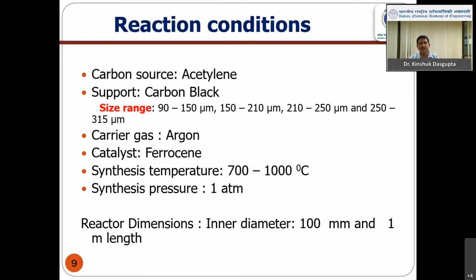So people generally they use like alumina, magnesia. These are costly materials and you require further processing steps to remove those materials from carbon nanotube. But in carbon black, first of all, carbon black is very cheap, and also you can remove them very easily, that I will discuss. So that is why we have used the carbon black. So by using these materials, you can really make the product a cheap product. If you use a raw material which are cheap, then you can end up with a product which are cheap. And carrier gas, we have used argon, catalyst, ferrocene. Ferrocene is a organometallic material which on heating will release iron nanoparticles. So generally synthesized in the temperature range of 700 to 1000 under atmospheric pressure.